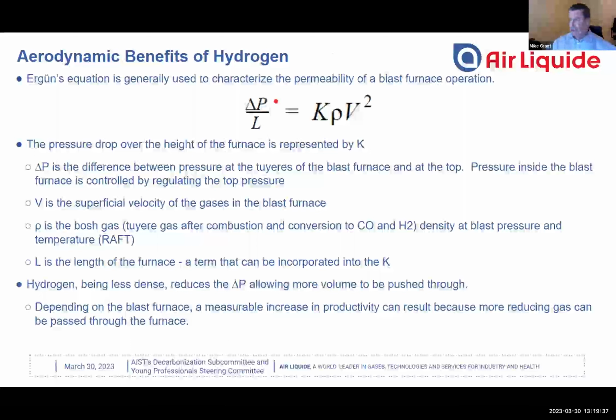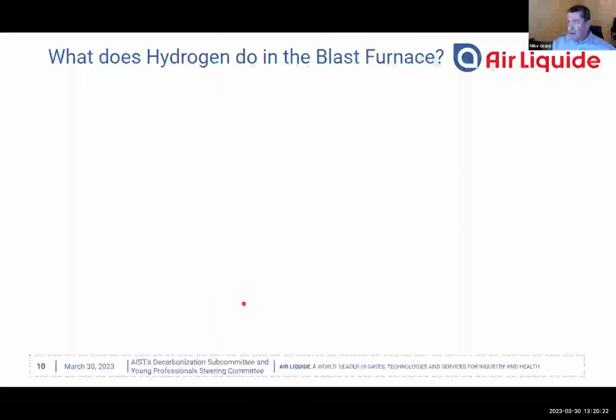Another limitation is the pressure drop from the tuyeres to the top of the furnace. This is dependent on a permeability represented by the constant K and the density of the gases inside the furnace. We call them bosh gases. As we put a lot of hydrogen into those bosh gases, this density goes down, which actually lowers the delta P between the tuyeres and the top of the furnace. And so this has, in some cases, allowed for a little bit higher productivity. And so not only do we see the CO2 emissions going down with hydrogen injection, but we also can experience some smoother operation. So what does hydrogen do in the blast furnace?